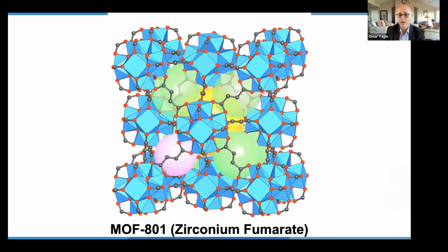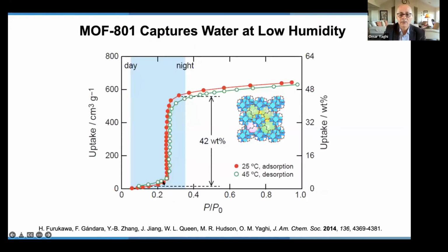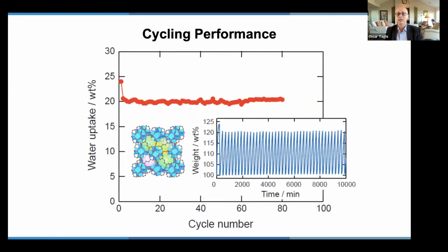Our first discovery of water harvesting in MOFs came while we were studying CO2 capture. As I said before, when you're studying CO2 capture, you're also having to separate CO2 from water. So we were also studying water uptake into MOFs, and this is the MOF zirconium fumarate, where we discovered that water is taken up at around 20% relative humidity, and it's taken up in this knee-shaped isotherm, which indicates a cooperative uptake of water. The amazing thing is not just that it has this cooperative knee-shaped isotherm, but that we can take the water out at 45 degrees C. And so immediately my thinking was that you could take this to the desert, extract water from air at night, and during the day when it heats up, you can take the water out and condense it.